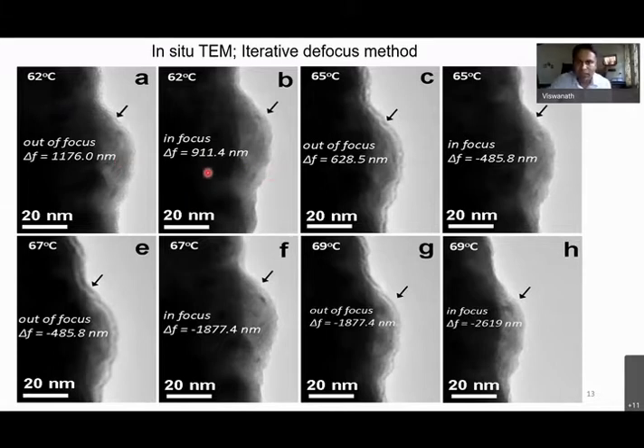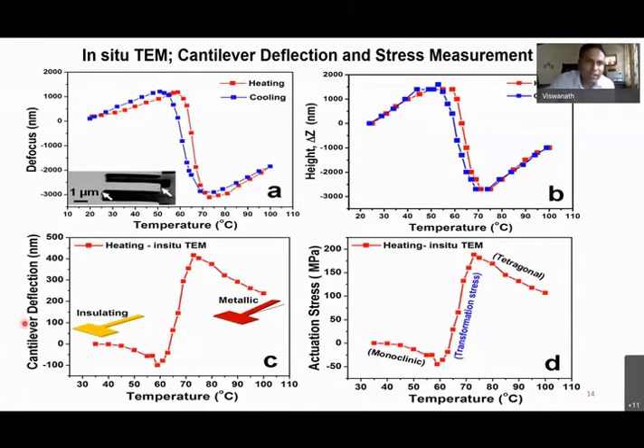I will change the defocus value, bring it back to focus again, then raise the temperature from 62 to 65. You can see here clearly the dark fringe coming. Again, change the defocus, bring it to focus, raise the temperature to 67. So by changing the temperature and correcting the defocus values, ultimately I'm able to get the defocus value as a function of temperature. And interestingly, in TEM, unlike other equipment, the defocus value can be controlled on nanometer scales. Even a few nanometers, I'll be able to fine tune my defocus value. So that way it is relatively precise.